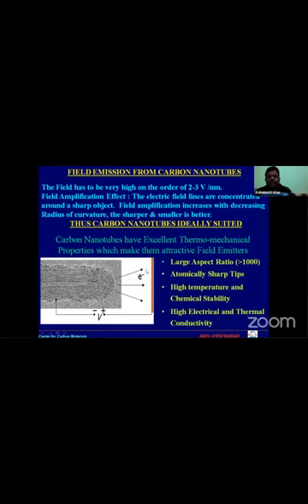It can emit the electrons because it has a very large aspect ratio, an atomically sharp tip, and high temperature and chemical stability, because you cannot make any material in nanometers that sharp mechanically. By any process, you cannot make it. So it is a very chemically stable material. Earlier, people were using the tungsten tip, but the tungsten tip used to be in micrometers, and tungsten was not chemically inert. All those challenges were there. So nanotubes have given a very strong set of properties to use as a field emitter.